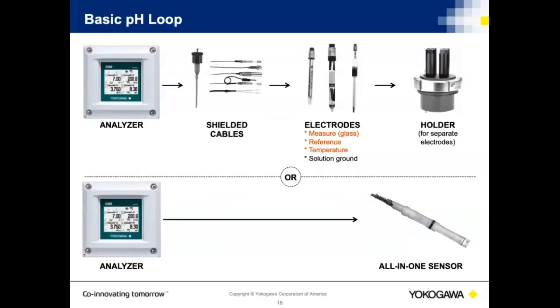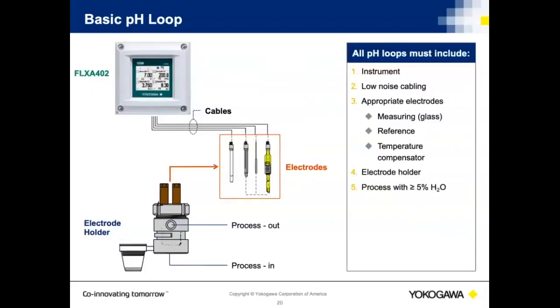The holder becomes very critical in high purity measurements because it must be made of stainless steel. When I look at the electrode set itself, it's always going to contain 4 different electrodes: a measuring electrode, a reference electrode, and a temperature compensator, as well as a solution ground. Basically, that probe set that you see there, the electrodes, can be put into an all-in-one sensor called a combination electrode. And that combination electrode can, at times, simplify the measurement. So it can be used depending on what the application is and where we're trying to make the measurement.